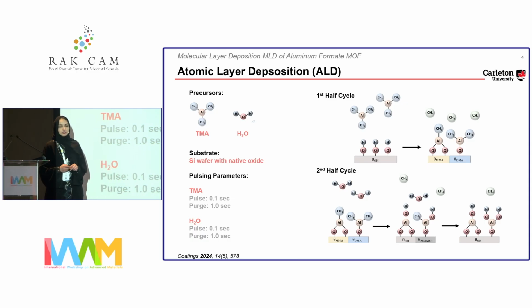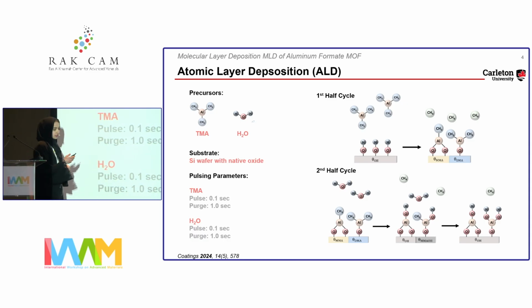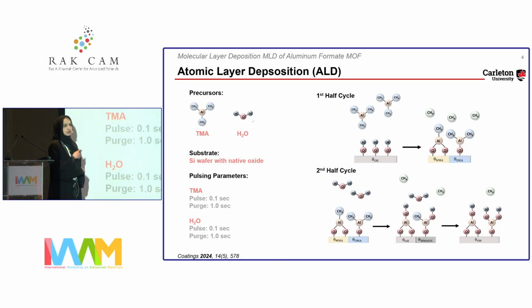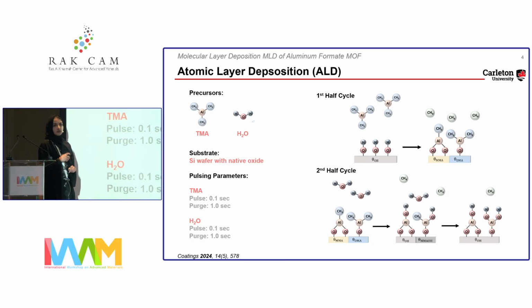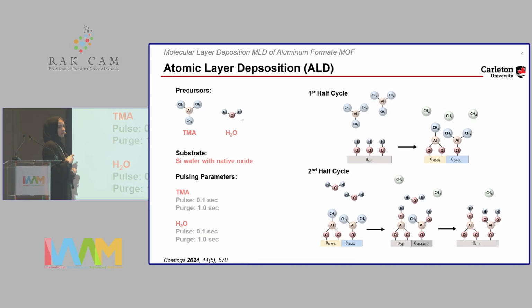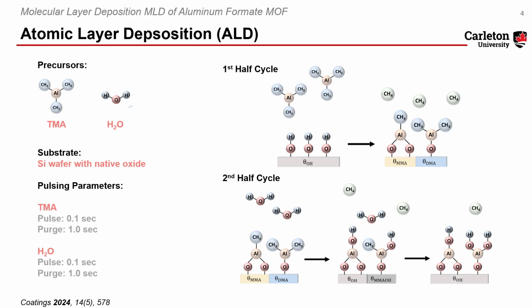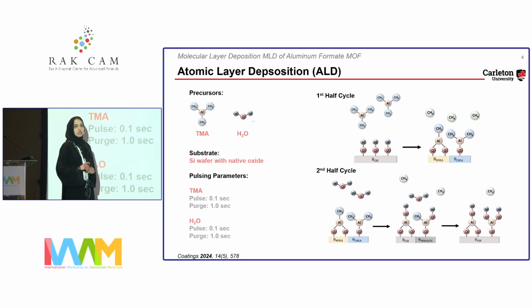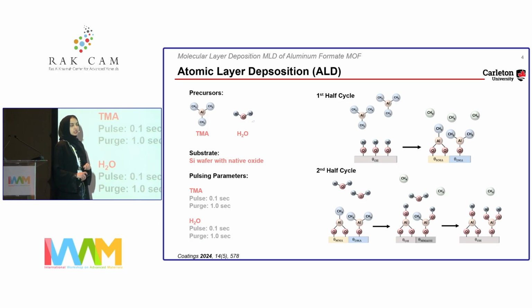Atomic layer deposition. This is just a brief overview. This is one of the most famous recipes in ALD. You make a thin film, an atomic layer at a time. So if you have this system of trimethyl aluminum and water, and you have a hydroxylated silicon wafer surface, you bring in the TMA under vacuum in a small dosage, and TMA will react with every last oxygen on the surface, if it's the right amount of dosage. And then any excess trimethyl aluminum on the surface gets purged outside the system. It does not accumulate on the surface. So it produces one single layer of aluminum on the surface.